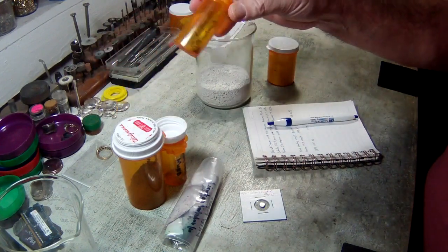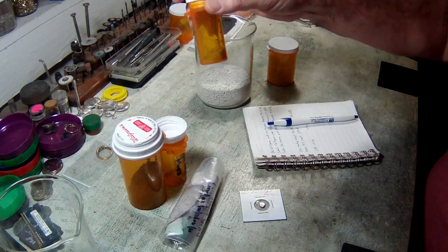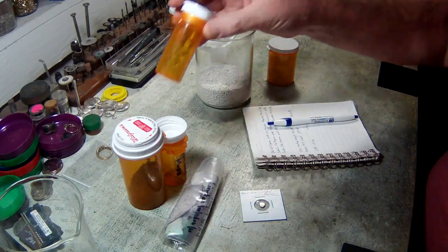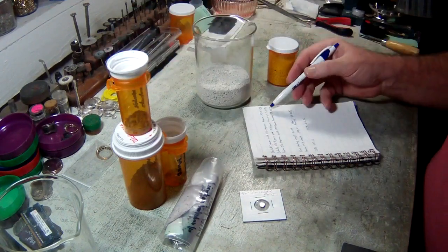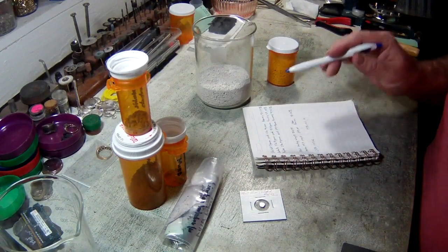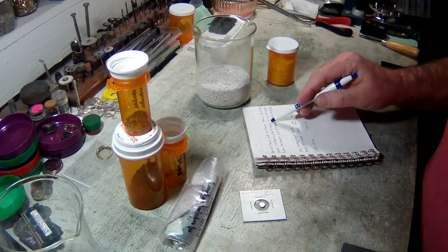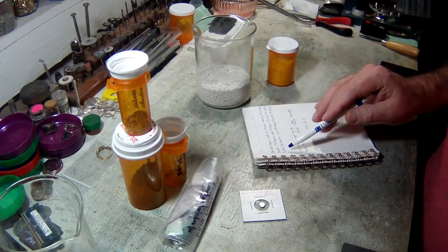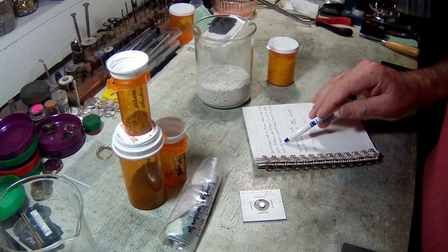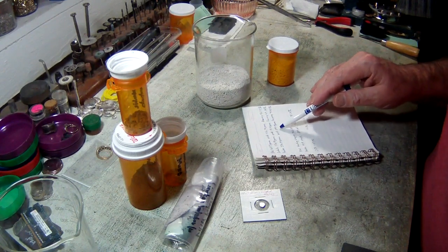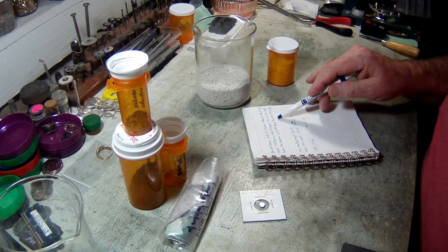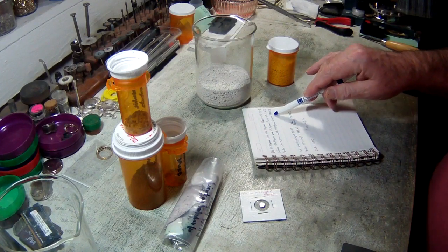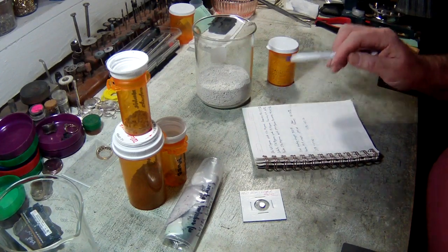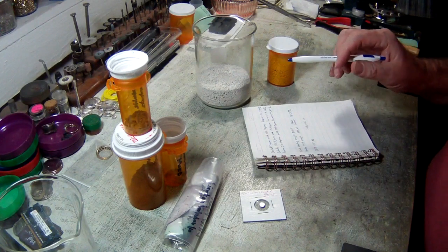I mean, you can figure when you've got contacts, you're going to have either tungsten or some other kind of metals in there. So to even get almost a 60% yield off the contacts was good, but the blob saved us there. And then the powder was 376.94 grams. It yielded 299.49, which was a recovery of 79.45%, which was actually better than our test.